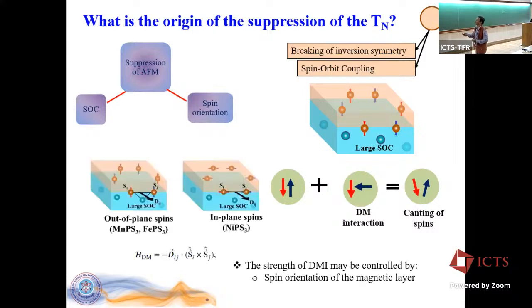Here you can see for MnPS3 and FePS3, the spins are out of plane and the DM vector is in plane. Therefore, the effective Hamiltonian will give you a non-zero DM interaction. But for NiPS3, the spins are also in plane, so all the vectors are in plane and they cancel out. That is why in NiPS3 we could not see any response even after putting on the substrates, but only for these two systems. So that positively guides us that there must be DM interaction getting invoked, which is why this suppression of the magnetic ordering is happening.